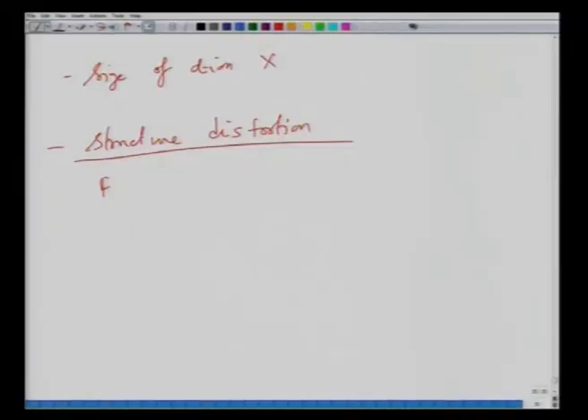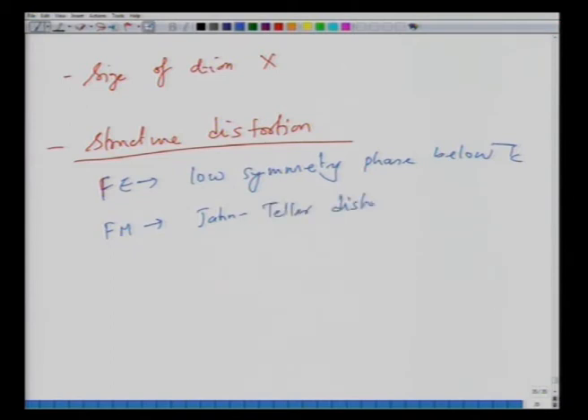So, ferroelectrics will have a low symmetry phase below Tc, and this requires breaking of the center of symmetry, and ferromagnets have Jahn-Teller distortion. I am talking about oxides only. So, here we are talking in the context of ceramic materials, not in the context of metals. These two are opposite requirements, because Jahn-Teller distortion requires the center of symmetry to be maintained and the low symmetry phase requires the center of symmetry to be broken. So, as a result, you have conflicting requirements. So, this is something which is interesting.